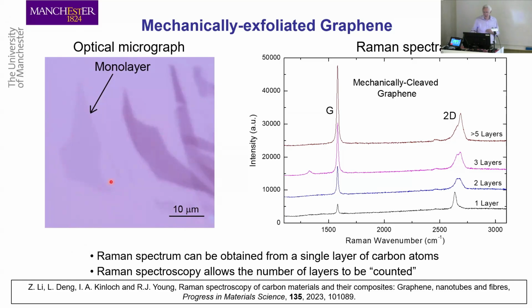Now, the nice thing about Raman spectroscopy is you can look at the Raman spectrum, which is the intensity of the scattering against the wave number, essentially the frequency of the light. And you can see that monolayer has a different spectrum than bilayer, has a different spectrum from trilayer, a different spectrum from 5 layers. So you can just put your specimen into the Raman spectrometer and you can see if it's monolayer, bilayer, trilayer, or whatever. We can actually just count the number of layers. So that's quite useful in characterization terms. And even though this is only 1 atom thick, so it's a 1 micron spot on a 1 atom thick material, you get a strong spectrum because the electronic structure of graphene is such that you get very strong resonance Raman scattering. So graphene is a material made for Raman spectroscopy. It's just the perfect material.